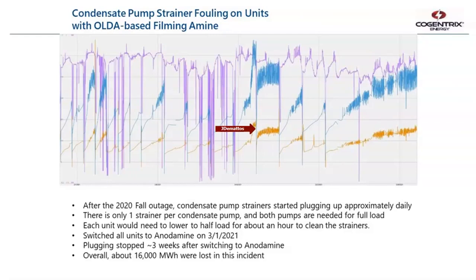it seems to me like it was a direct result, and again it's winter time, and we did see colder exhaust duct temperatures during this period of time. So it might be something where it works fine when it's hotter and it's not so good when it's colder. But this was the only one of the 4 units that we saw condensate pump strainer plugging up. Overall, from this incident, we lost about 16,000 megawatt hours. How severe that is, I guess it depends.